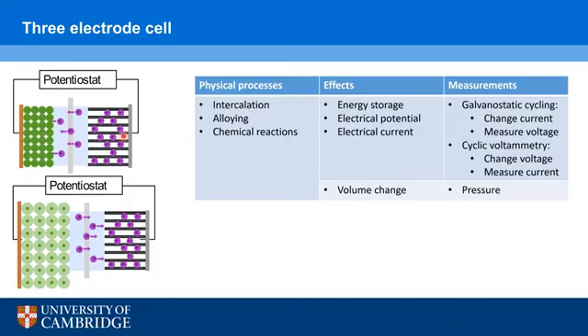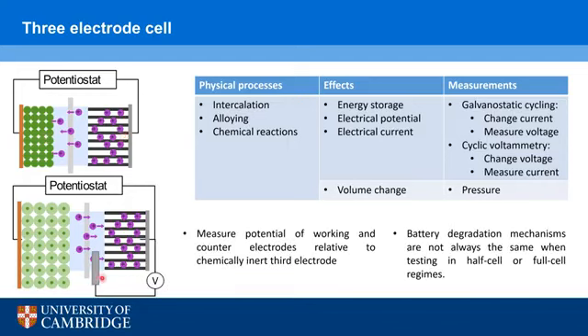So what we can do is use a three-electrode cell by introducing a third reference electrode, which in a lithium-ion battery would be a lithium metal electrode. And then by measuring the potential difference between the anode and the reference electrode and the cathode and the reference electrode separately, we can track the potential changes of both electrodes separately. And this is important because then we can track the chemical changes in something that simulates more closely a full working battery. Also, in terms of studying new materials, the battery degradation mechanisms are not always the same when testing in half cell and full cell regimes.